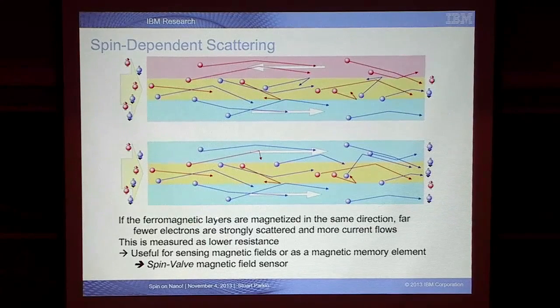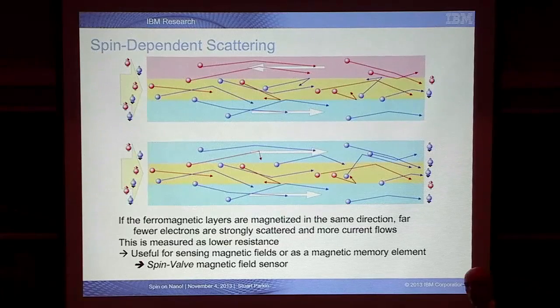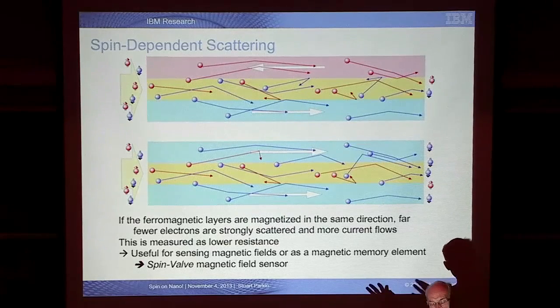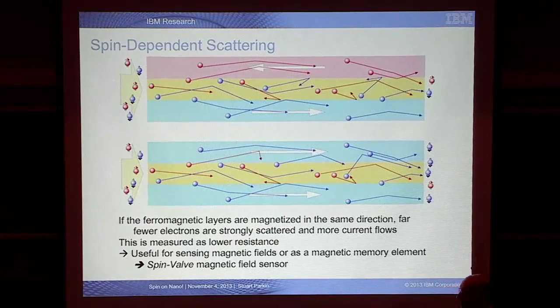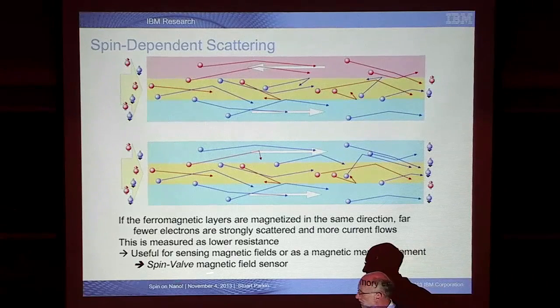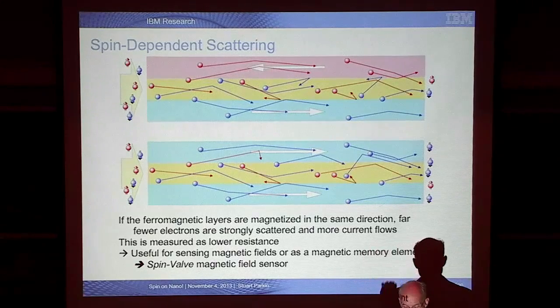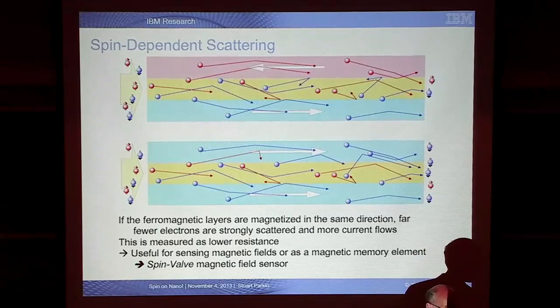So in this case, each of the magnetic layers prefers that the electrons are colored blue. So in this case, effectively, we have a short circuit through the sandwich. The blue electrons can travel very, very easily. So the resistance of this configuration will be lower than the resistance of the upper configuration. And essentially what this is, and what we called a spin valve, because essentially we're turning on and off currents of spin-polarized electrons. So it's a very simple concept.